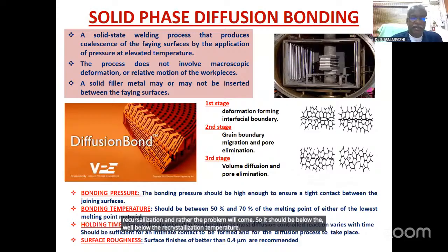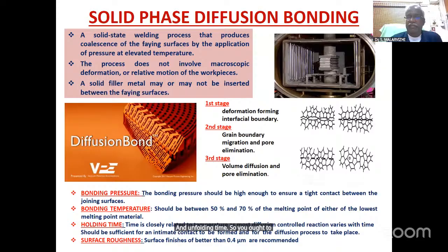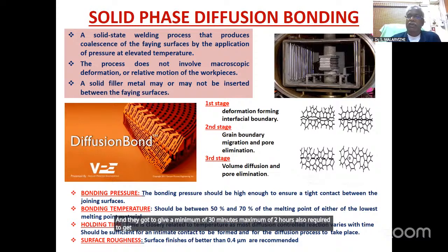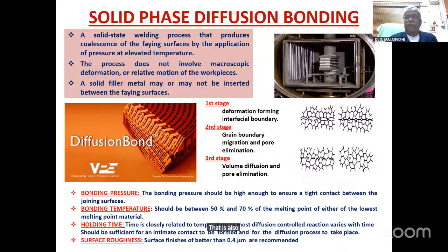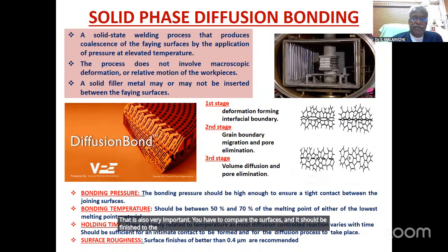And holding time. So you have to give sufficient time, because it's a slow process, and you have to give a minimum of 30 minutes, maximum of 2 hours also required to get good quality bonding. And the surface roughness, that is also very important. You have to prepare the surfaces, and they should be finished to a surface roughness of 0.4 microns.